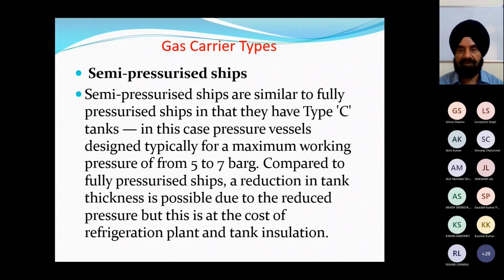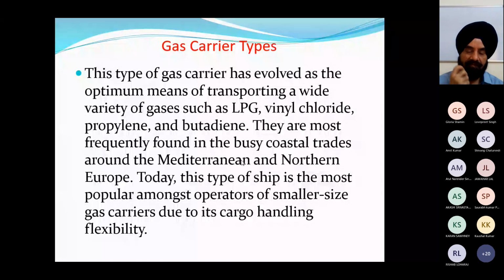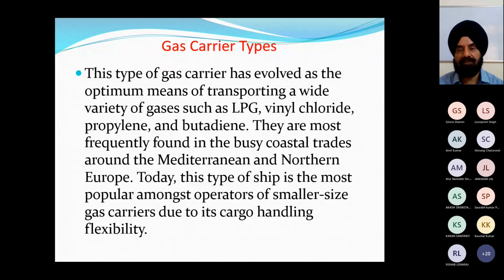Now semi-pressurized means the ships are similar to fully pressurized, type C tanks, and in this case pressurized vessels designed typically for lesser pressure. There it was 20 bar, here it is 5 to 7 bar compared to fully pressurized ships. So there is a reduction in tank thickness due to the reduced pressure, cost reduction also, plus refrigeration plant and tank insulation are also needed, because they are semi-pressurized and semi-refrigerated. So this type of gas carrier is an optimum means of transporting a wide variety of gases such as LPG, vinyl chloride, propylene and butadiene, most frequently found in busy coastal trades in the Med Sea and Northern Europe. It is the most popular amongst operators, these semi-pressurized ships.